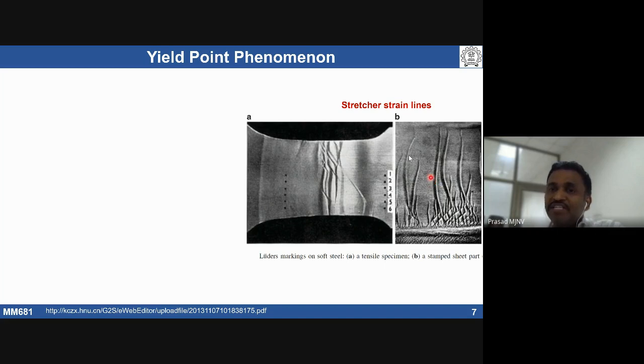The formation and presence of these stretcher strain marks is basically a result of the yield point phenomenon. Whenever there is yield point elongation, it can give rise to these stretcher strains. So this formation of stretcher strains is considered a problematic thing for a component that has been fabricated without overcoming this problem.